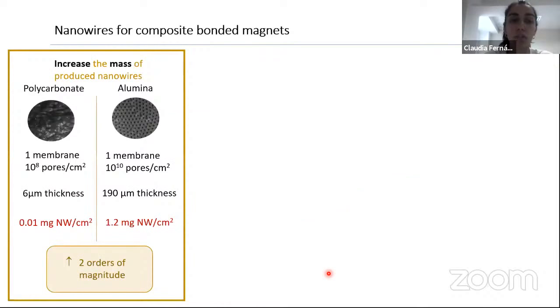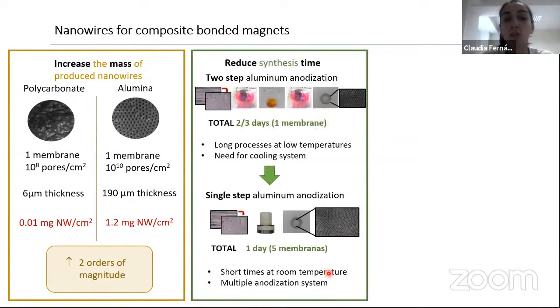So first of all, to increase the mass of the produced nanowires, we decided to change from polycarbonate templates to alumina. This allowed us to increase the pore density of the templates and also their thickness. And we were able to increase by 2 orders of magnitude the quantity of nanowires that we were able to produce. To reduce the synthesis time, we have focused on reducing the synthesis time of the template because it was the most time-limiting process.